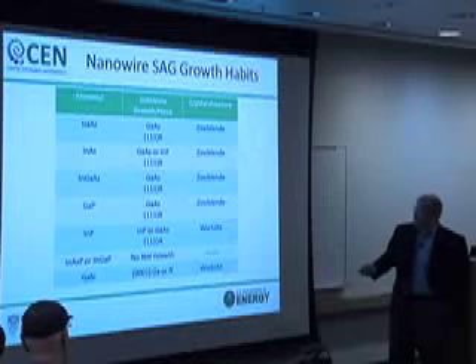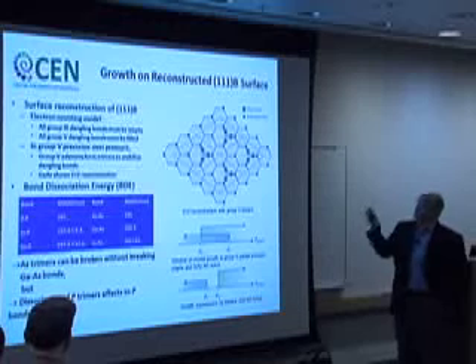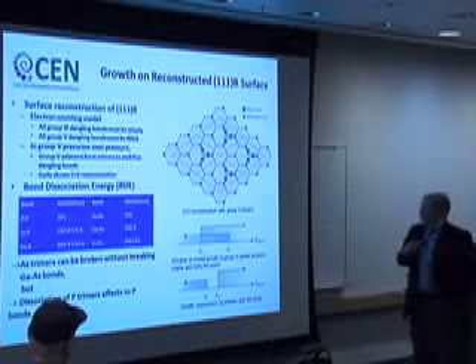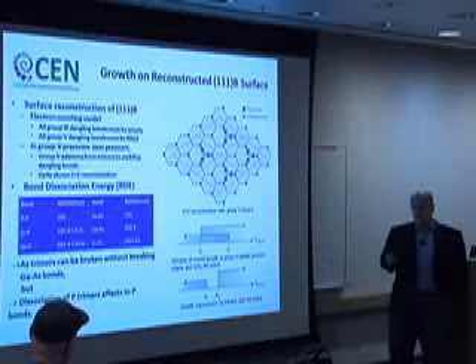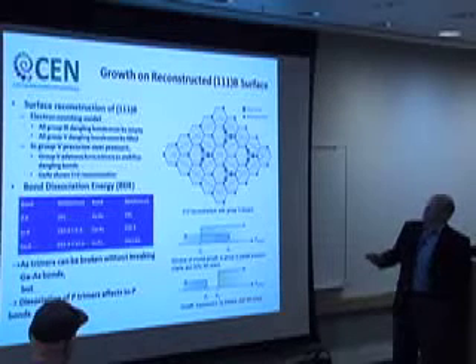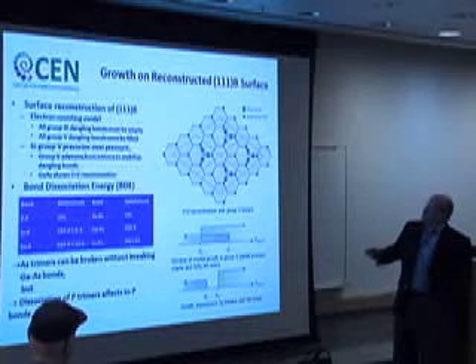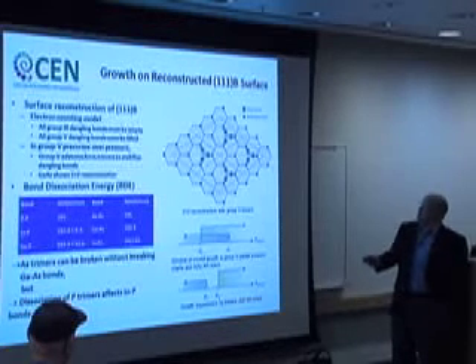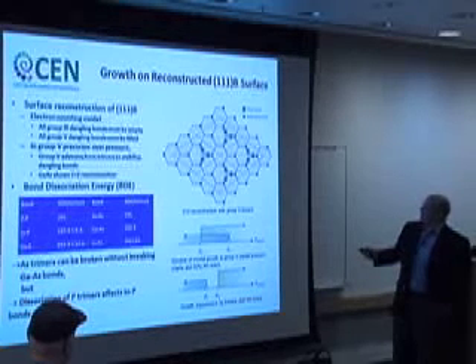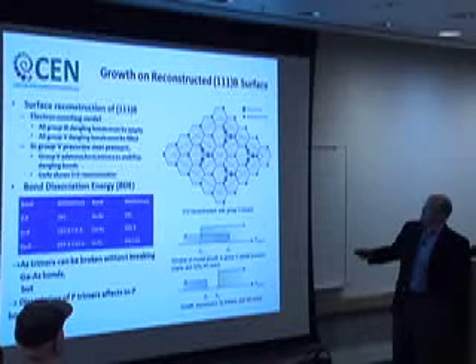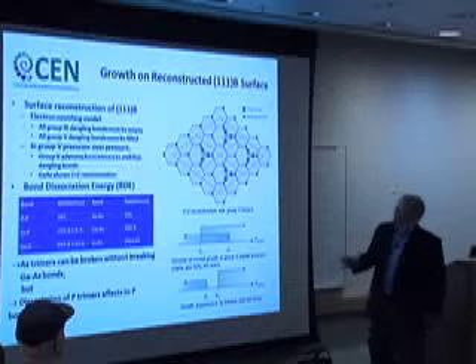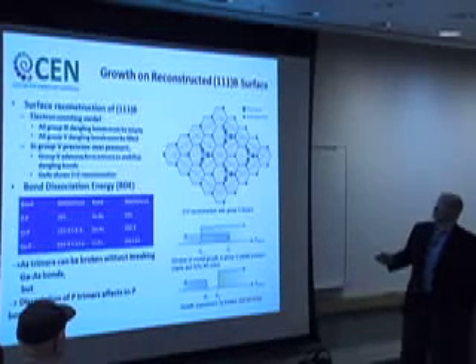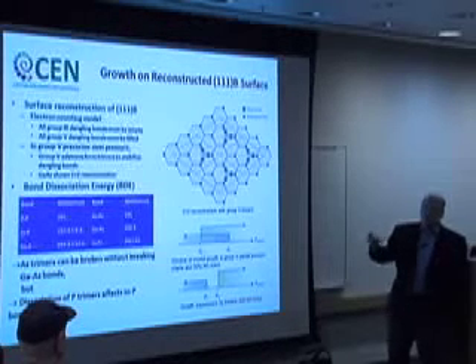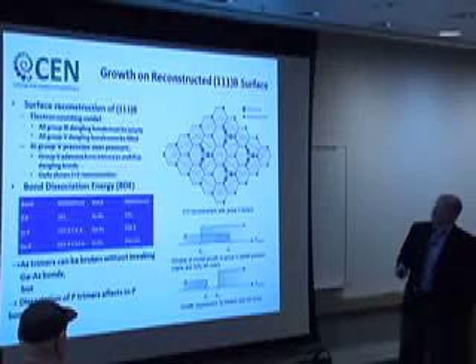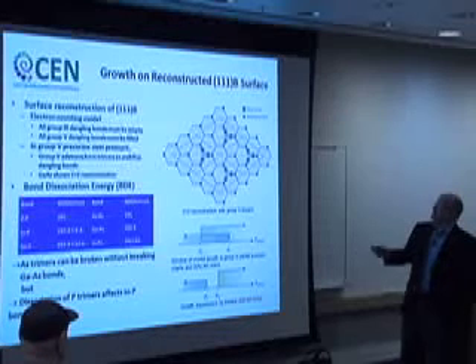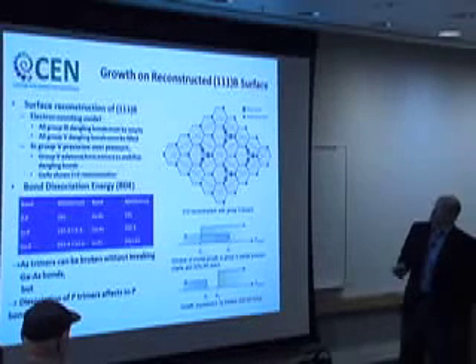So we looked into why this might be happening, and this is kind of a busy view graph. You have to accept the idea, which we borrowed from the MBE literature, actually, that when you grow on this particular facet, the 111B facet, the surface reconstruction is such that the surface is stabilized when there's an extra layer of column 5 atoms on the surface in the form of trimers that are bonded to the surface. And this gives you a 2x2 reconstruction, and this is very well established in the MBE literature. Of course, we don't have the ability to look at those kinds of structures in the MOCVD system. So we're hoping and assuming that that's what happens in MOCVD as well.